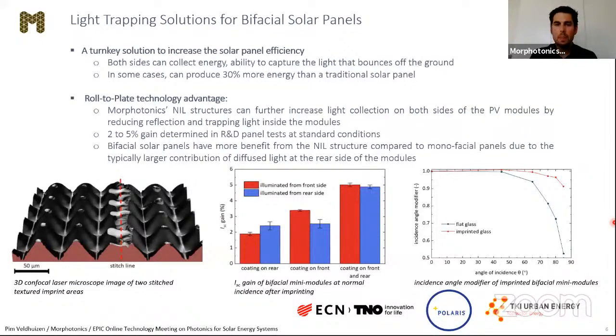Interestingly, if we apply the texture on both interfaces, the front and the rear, the benefit adds up to about 5% of current gain. You can see this in the center graph, and this is all measured at standard test conditions. But usually, solar modules are not operated at standard test conditions. In the field, they are also receiving light that is off angle.